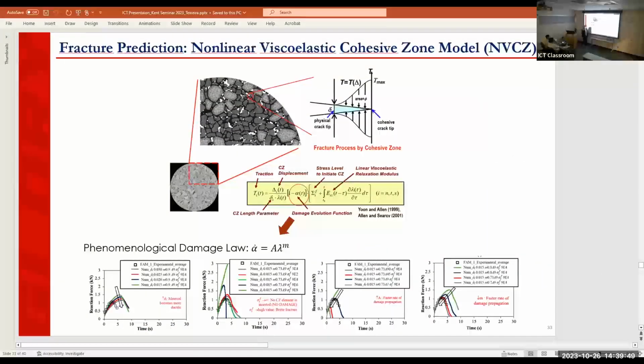Before showing the result, let me just talk briefly about the numerical model that we use. We use a micromechanical model based on fracture mechanics, where we can evaluate the crack initiation and propagation explicitly. It's not an indirect way, it's a direct way to see when a crack starts and when the crack starts to propagate.